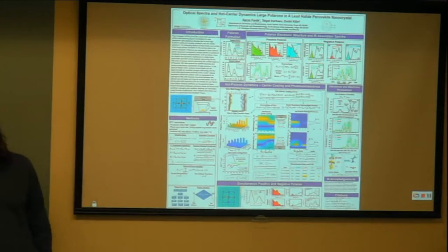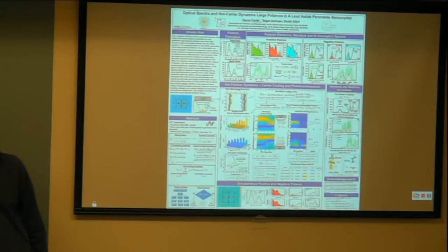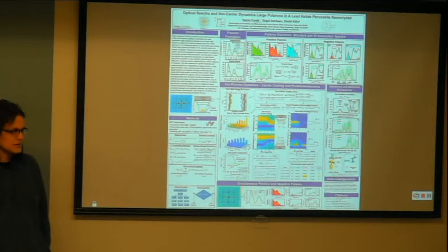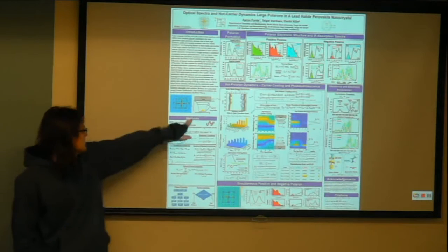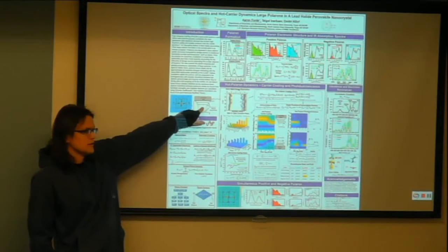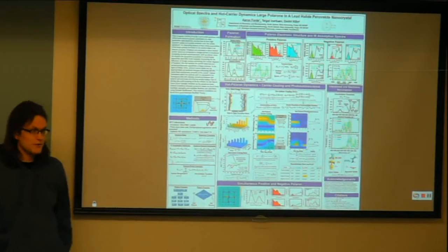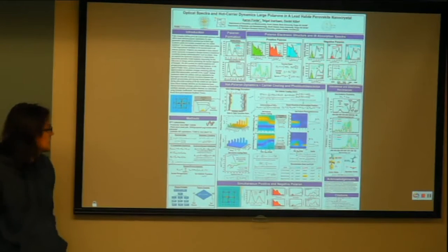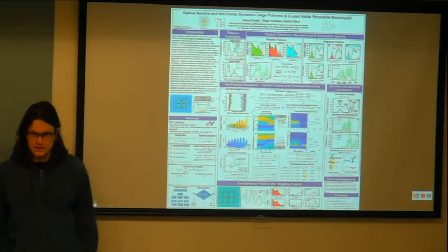So the challenge is describing the radiative and non-radiative parts. And I forgot to mention the most provocative thing that we tried to model is polaron photoluminescence, and to measure its efficiency, whether it could be an efficient emitter, because it's suspected these energy gaps are in the IR range. So if you can get an efficient IR emitter from the polaron, that would be an interesting potential application for these.